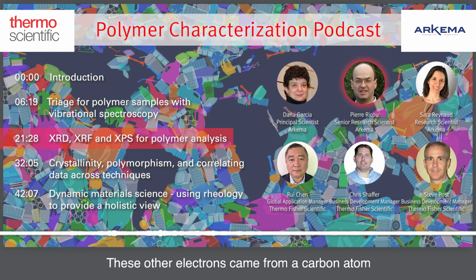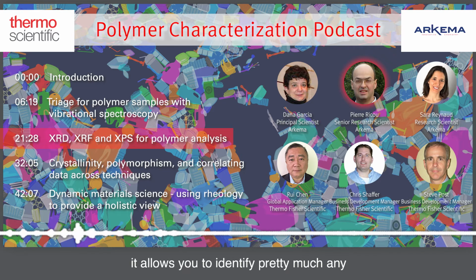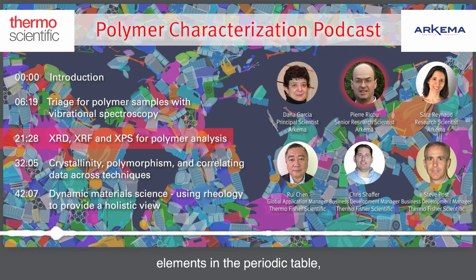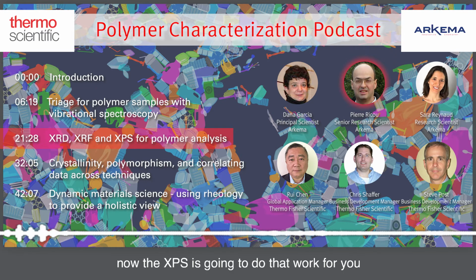Did that electron come from a carbon atom or an oxygen atom, or was it silicon or titanium, iron, etc.? So it's a very powerful technique. It allows you to identify pretty much any element in the periodic table. There are just hydrogen and helium, the first two, that cannot be done. But any other elements can be identified and quantified, similar to what an XRF would do for the bulk. Now XPS is going to do that work for you for the surface. Because you're looking at electrons and they don't travel very far in a material, you're extremely surface sensitive, like the top 5 to 10 nanometers of the sample surface.